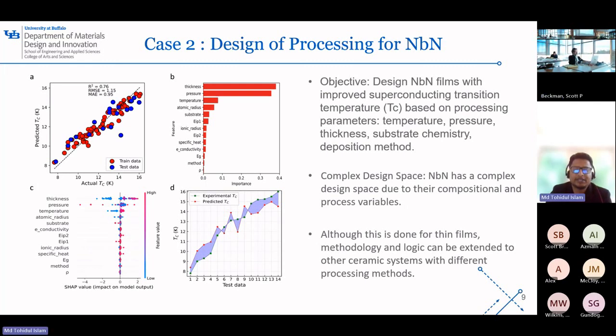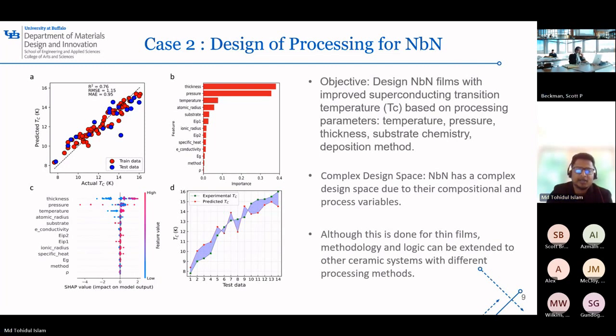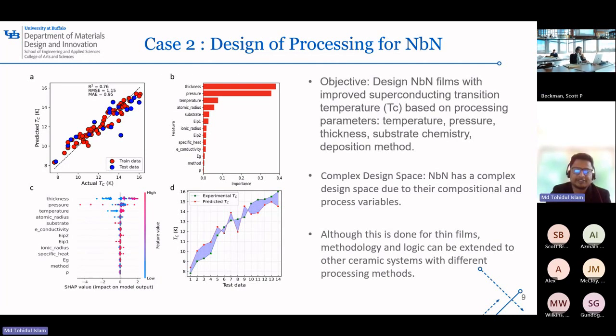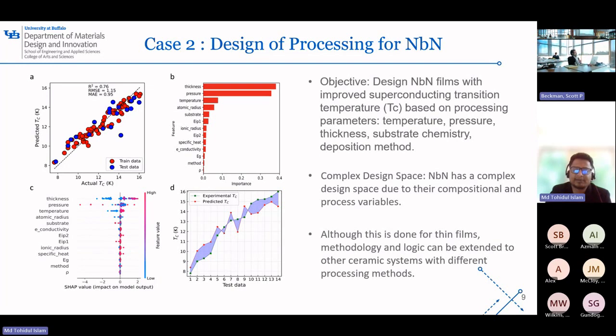This is our second case study where we optimize the processing and chemistry for niobium nitride. Our goal was to enhance the superconducting transition temperature by tweaking everything during the deposition process — from the substrate temperature to the chamber pressure, and even the thickness of the deposited film. The cool part about this methodology is that what we learned here can go beyond the niobium nitride system; we can apply the same approach to other ceramic materials and fine-tune the process to get the properties we are looking for.